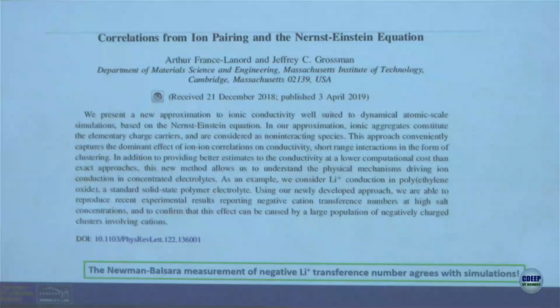But there are others who took us more seriously. Here's a paper that came out of MIT from Jeff Grossman's group, where they said they developed a new way of doing molecular simulations. That paper, by the way, ignored the fact that we had derived things. They didn't say this is the flaw in the derivation. They just said we were wrong and they don't care. This paper says that they have developed new techniques to measure the transference number, and that experimental results, which were ours, reporting negative cation transference, are confirmed. So there's debate in the literature about what is right and what is wrong.